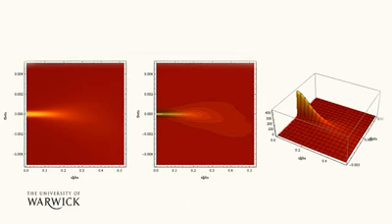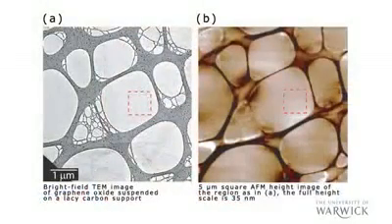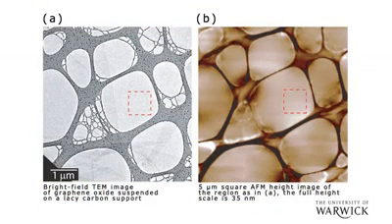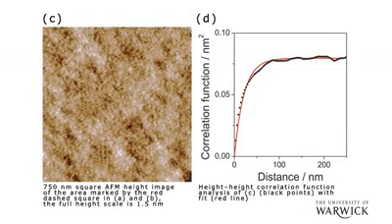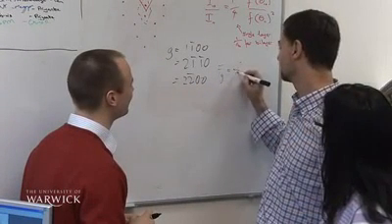From our investigations, both AFM and electron diffraction clearly indicate that the topography of graphene oxide is different to that previously reported for graphene. The local strain induced by the functionalization causes short-range corrugations in the graphene-like lattice of graphene oxide, and the magnitude of these distortions is about a tenth of the carbon-carbon bond spacing. Reduced graphene oxide appears to be similar, consistent with observations that its conductivity is orders of magnitude lower than mechanically exfoliated graphene. The local strain will have important implications both for the mechanical properties and for the chemical reactivity.